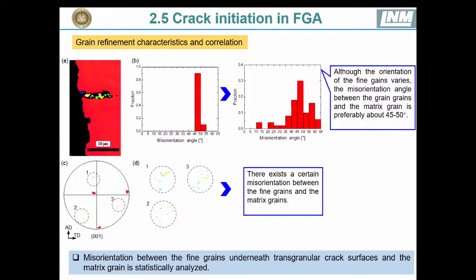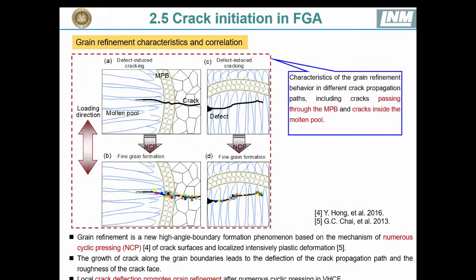Therefore it is reasonable to believe that there will exist a certain misorientation. And then the angle of this misorientation tends to be between 40, 45 and 50 degrees. And for the grain